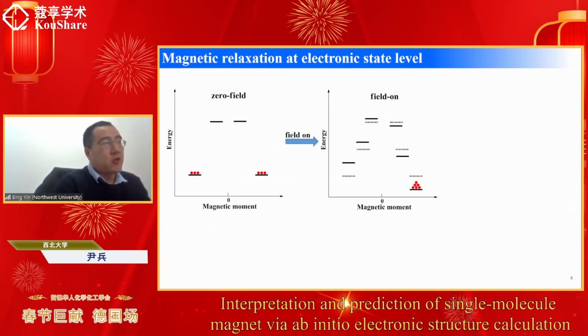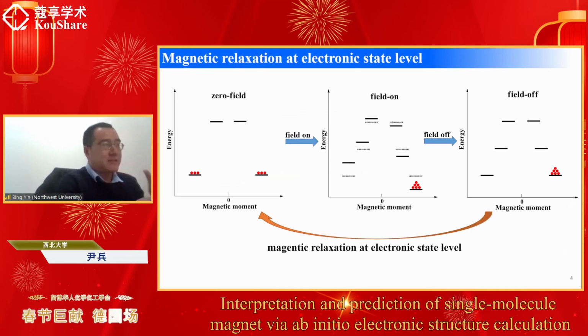And then we apply the magnetic field for a long enough time, and the degeneracy of the electronic states is broken. So all the population will go to one special state, of which the magnetic moment is along a certain direction. So the system will show magnetic moment. And then we switch off the field, the energy levels become degenerate again, but the population is not in equilibrium. And so the system will finally go back to the zero field case, which is in equilibrium. So this process from a non-equilibrium state back to the equilibrium state is called magnetic relaxation at the electronic state level.